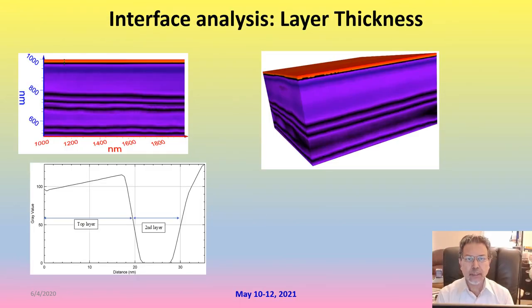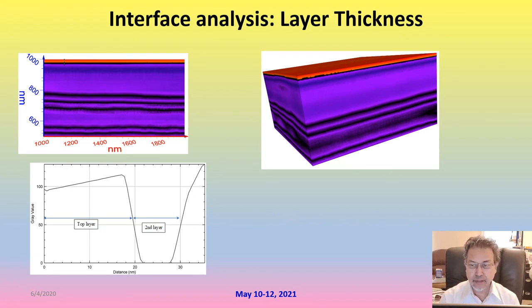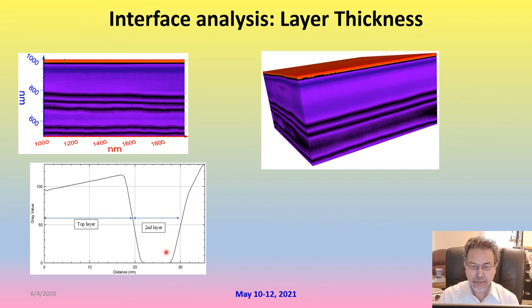Here are examples of interface analysis. When it comes to interface analysis, the first thing we need to do is measure the thickness of the layers — whether it is an epitaxial semiconductor or some other deposited layer. Taking a three-dimensional picture, we can extract a single plane and measure the thickness of different layers. The very top two layers are shown here: one is about 18 nanometers, and the other is about 10 nanometers. The 3D image also shows some imperfections of the layers.